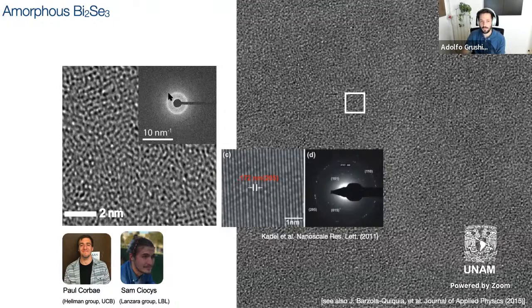And if you have a polycrystal, what you would see is actually not a smooth ring, but some peaks, in fact, so the intensity would not be uniform around the ring. I don't think I have the diffraction pattern of a polycrystal. But essentially, if the crystalline domains are sizable or detectable within your experimental apparatus, then you'll see speckles in this ring. If you have different domains, you basically do an angle average, but this angle average would not be very uniform, particularly if you look locally. And so that's how people distinguish.